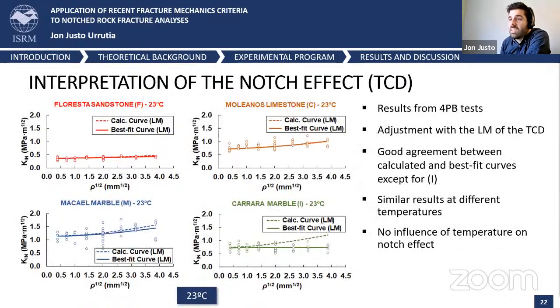These plots represent the variation of the apparent fracture toughness with the notch radius. So it somehow represents the existing notch effect. Each dot corresponds to the values of each of the performed individual 4-point bending tests. And the notch effect is interpreted in this case according to the theory of critical distances and, in particular, to the line method. The dashed lines represent the calculated curve according to the line method.